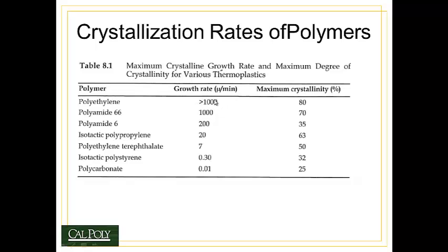Let's take a look at some actual data. Here we have polyethylene, which has a relatively high growth rate because it's a simple molecule, and therefore it has a rapid rate of diffusion, and it is able to nucleate readily. Notice also that it has a very high maximum crystallinity percentage of around 80%. By comparison, more complex polymers, such as polyethylene terephthalate and polyethylene...